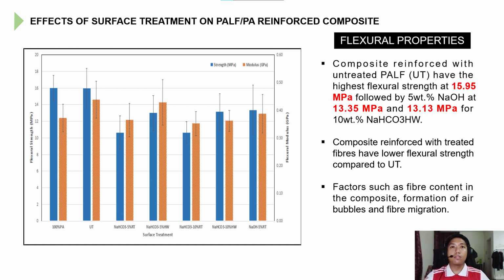Next, we have the flexural properties of the pineapple leaf fiber PA reinforced composite. Over here we can see that the flexural strength of the untreated fiber is the highest compared to the treated fibers. Theoretically, the untreated fiber is supposed to have the lowest compared to the treated fibers. However, in this research, in my research,